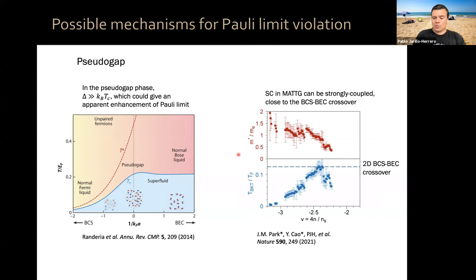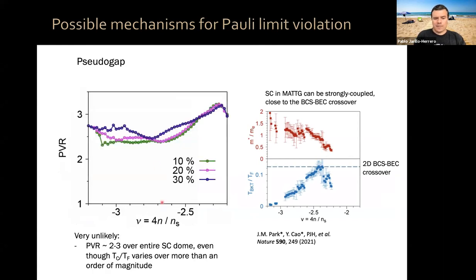However, we also observe a large Pauli limit violation away from the strong coupling limit, in regions where our TBKT over TF is very small. So we're in a weak coupling limit, okay, which we can tune electrically. The Pauli limit violation is always above 2, kind of 2.5 and up to 3 point something. Okay? So we think again that although a large pseudo gap, preformed pairs, might be an explanation for it, it's unlikely to explain our data because of the pervasiveness of the observation of the Pauli limit violation.